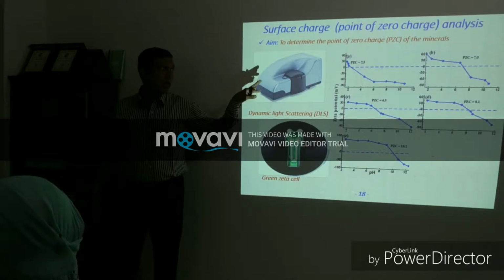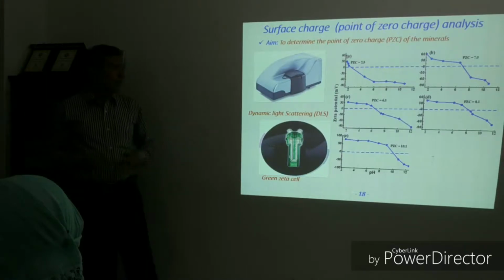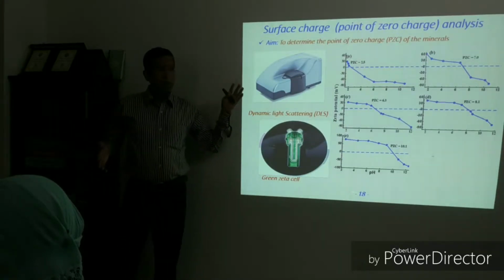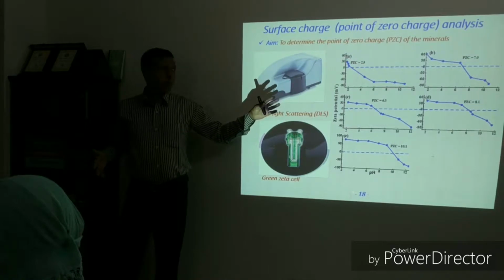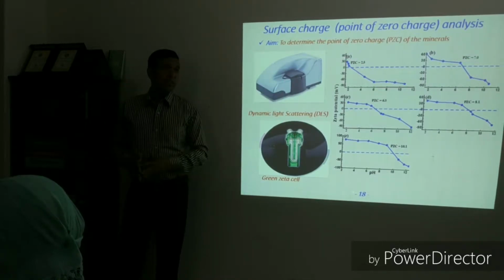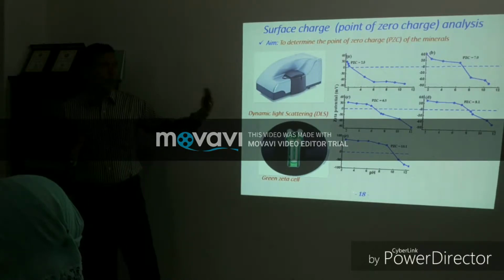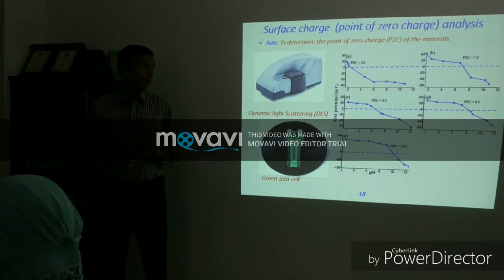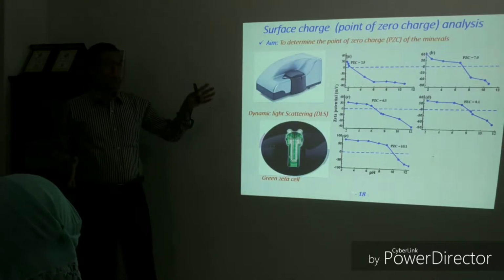Then, point of zero charge. This is very important for adsorption study because manganese oxide minerals are amphoteric in nature, and due to change of pH, these surfaces are protonated and deprotonated, producing positively and negatively charged surfaces. However, at a certain pH, the concentration of positively charged surface and negatively charged surface are equal. That pH is known as the point of zero charge.